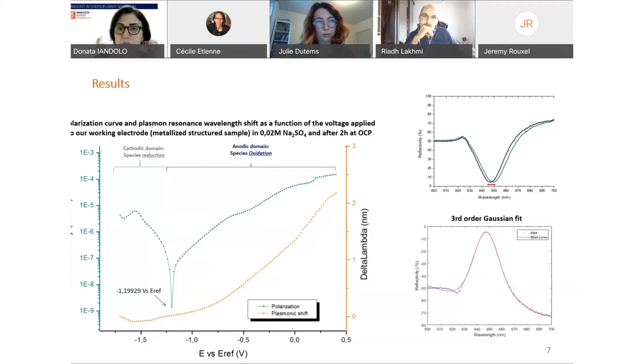By studying the shift in the resonance wavelengths, it is linked in all the plasmonic equations to the growth of a film. And we do have software with a calculus code based on a Chandezon equation, where it is possible to simulate the response of our gratings, and hence the growth, for example, of alumina. But in that case it's not pure alumina. It is composed of hydrated aluminium oxide. So I don't know if it answers your question.